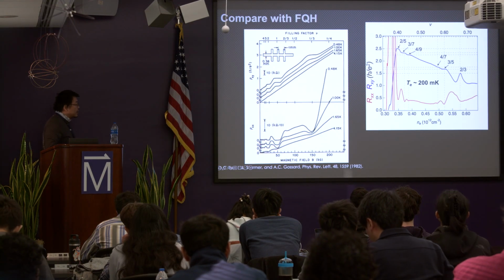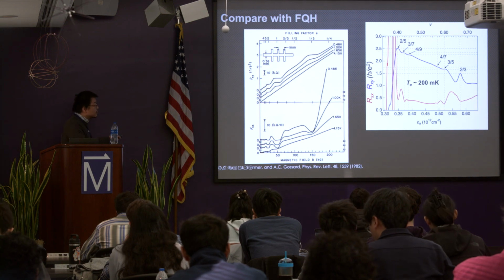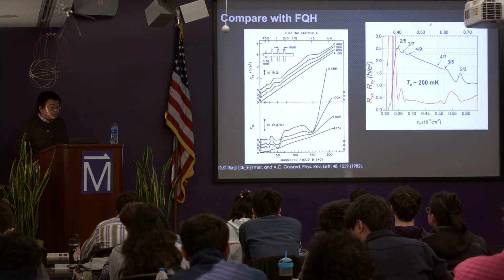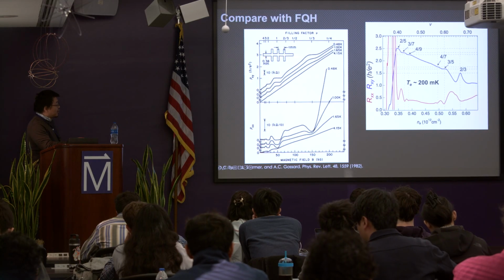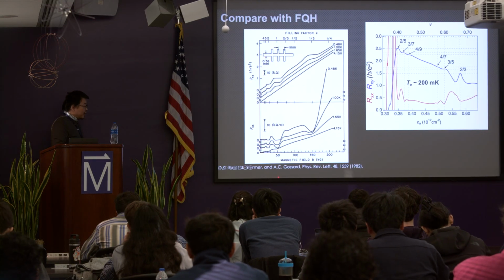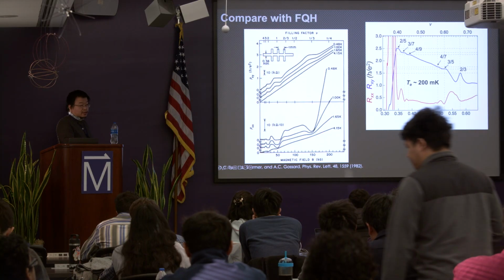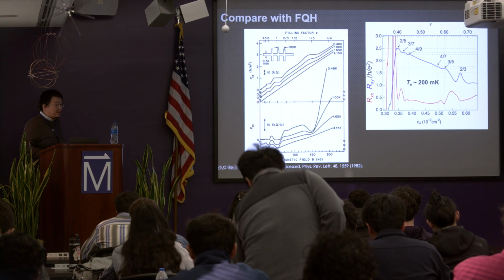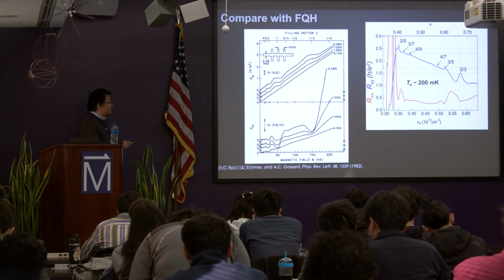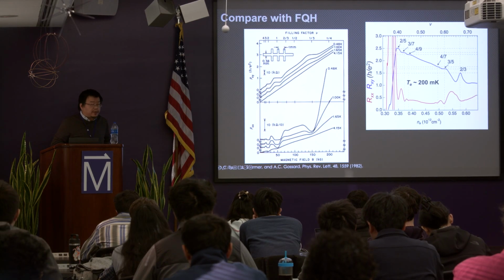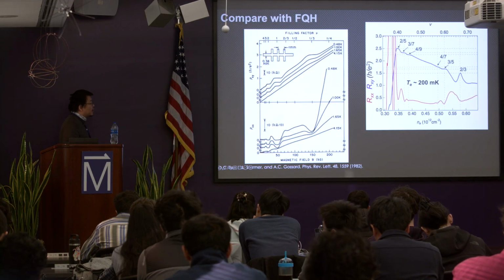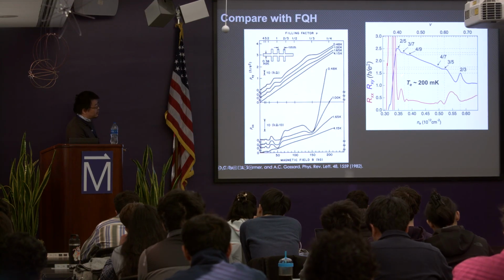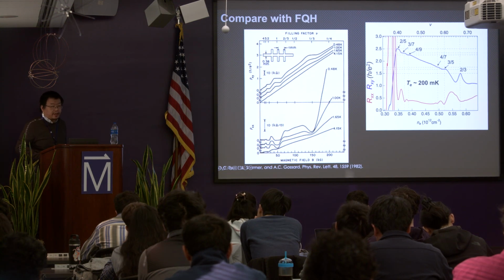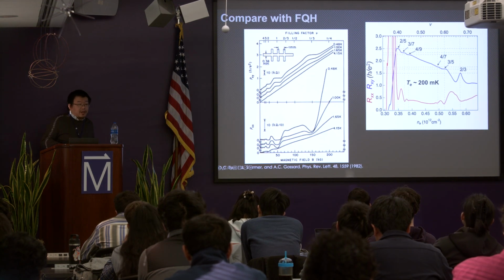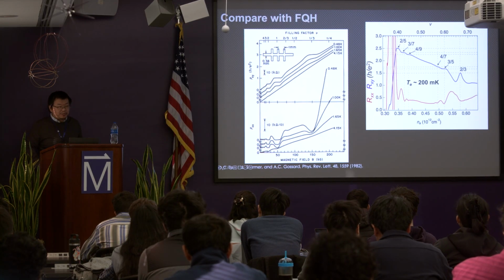So okay, if we compare with the first graph from the fractional quantum Hall effect, there's also a pretty good quantization for RxY and a not so small RxX. If we compare the two, they're more or less similar in terms of how good the quantization is and the rough RxX value, or RxX residue. Also these two measurements are done at a relatively similar temperature, on the same order of hundreds of millikelvin. So the good thing is the fractional quantum Hall community has been so successful, and we can just learn from them how to improve everything.